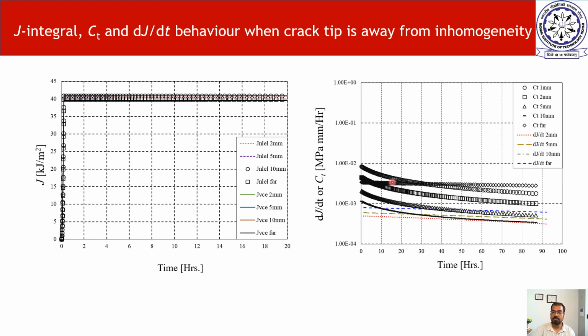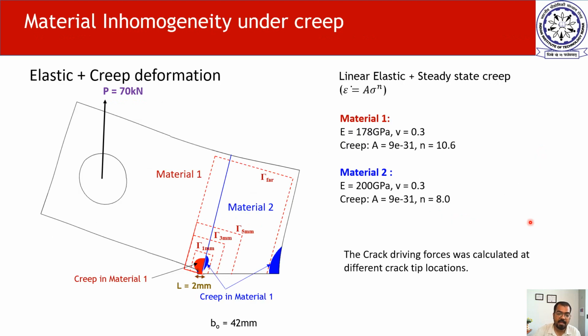And here in this plot you see the CT integral, which is not path independent. And this is because even though the time is significantly larger, so we have simulated for 100 hours, because the creep zone is very small, it is not extensive creep condition, and that's why it is showing path dependence for the CT integral. But if you see the dJ/dt, that doesn't show that much path dependence. The blue line shows a value much different from the other values because there is a back face creep.